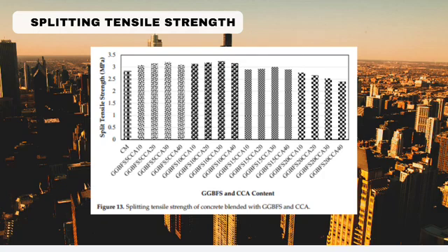Again, the splitting tensile strength of concrete was investigated with the addition of 5 to 20% GGBFS by the mass of PC and 10% to 40% of CCA by the weight of FA together in concrete. The best indirect tensile strength was observed at 3.22 MPa at 10% GGBFS along with 30% CCA, and the lowest value was documented at 2.40 MPa at 20% GGBFS along with 40% CCA together in concrete at 28 days.